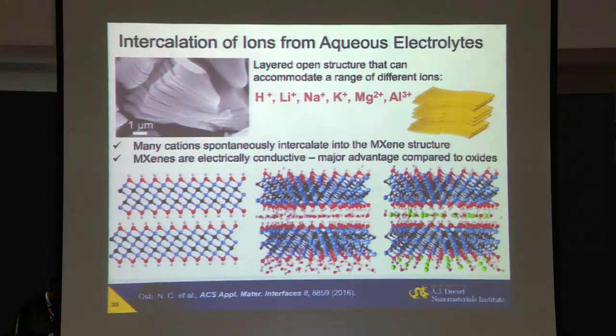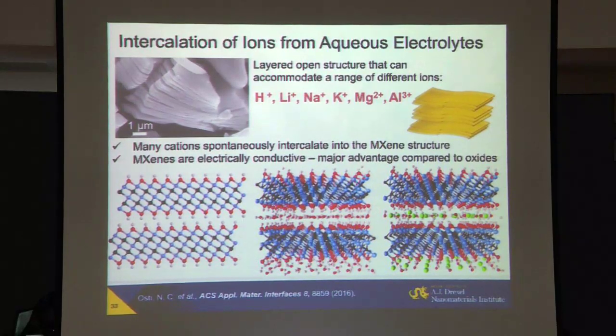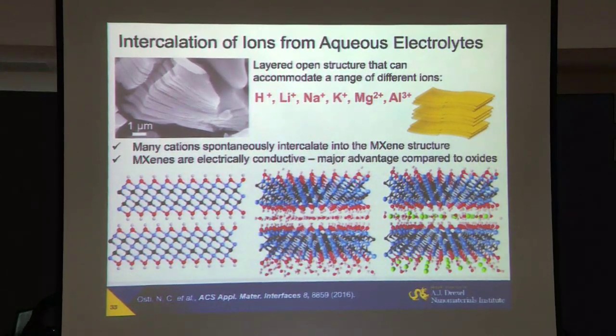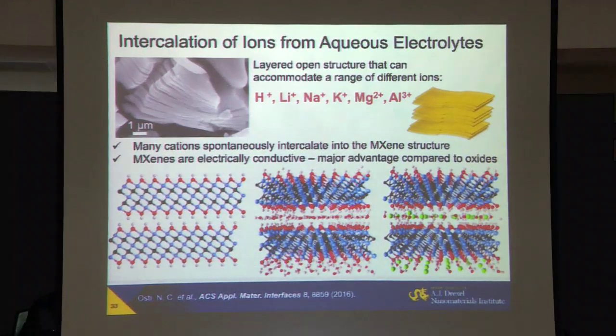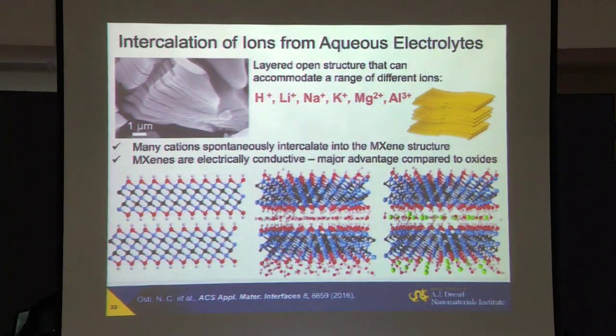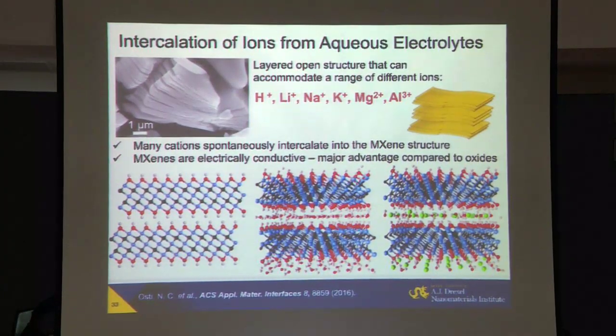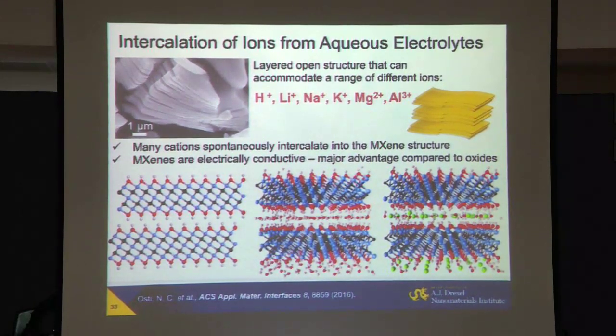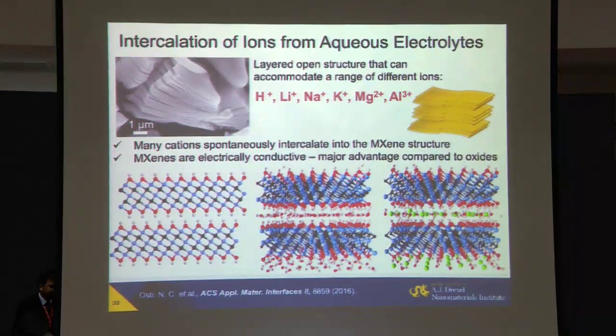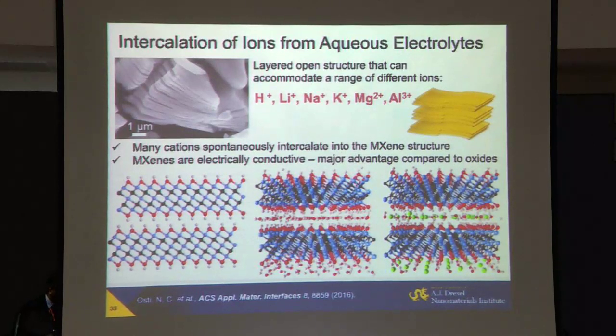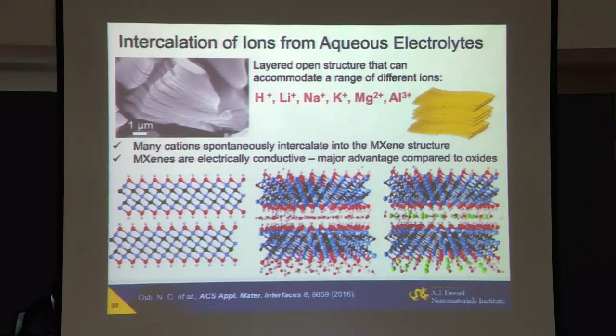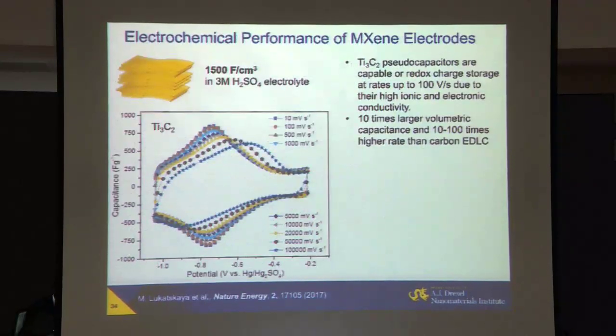Moreover, you know, Elon Musk promised that Tesla batteries will be charged within 5 to 10 minutes when you come to a charging station. What does quick charging mean? It means a very simple thing. You have to run very high current through the battery. Currently, people use, for example, oxide material for cathodes, and even graphite that you use for anodes is not very conducting. So what happens if you run high current through a resistor? It just heats up and explodes. So this is the type of material we need to have very fast charging.